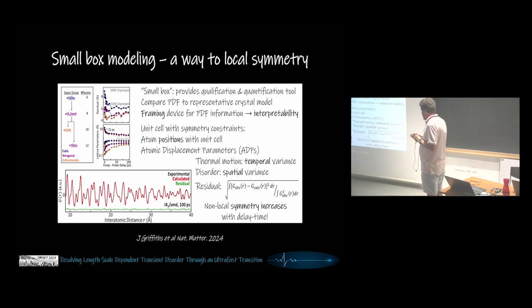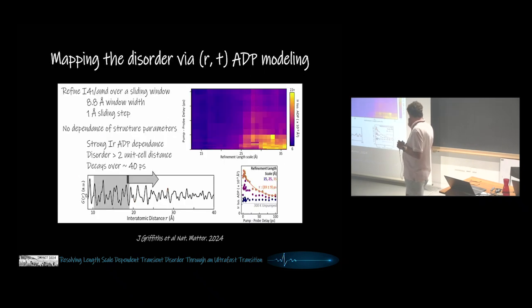And that change happens over the time scale of about 12 picoseconds. Another important aspect of PDF analysis is focusing on atomic displacement parameters, because in the case of thermal motion, they give you temporal variance, but in the case of disorder, they actually capture spatial variance, and that's what we utilized. And so this is what you get.